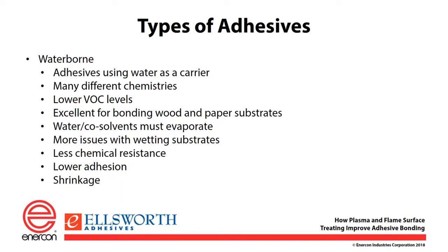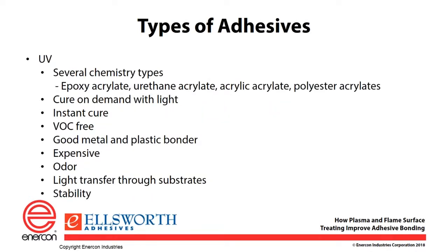Wetting can be an issue. That's because water has a surface tension of 72 dynes. So if you're bonding to plastic, for instance, that's much higher than the surface tension of plastics. So you need to use additives or your co-solvent package to make sure that you get the surface tension of your material low enough to wet out the substrate. They generally have less chemical resistance than their solvent-borne counterparts, generally have a little lower adhesion, and shrinkage is still an issue.